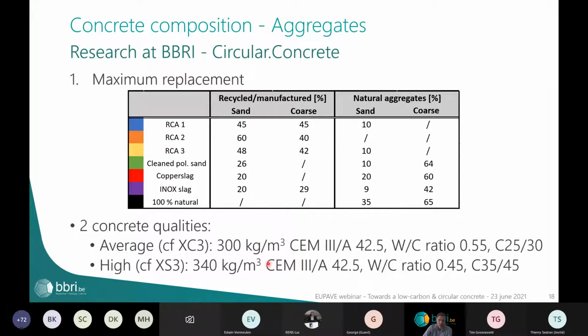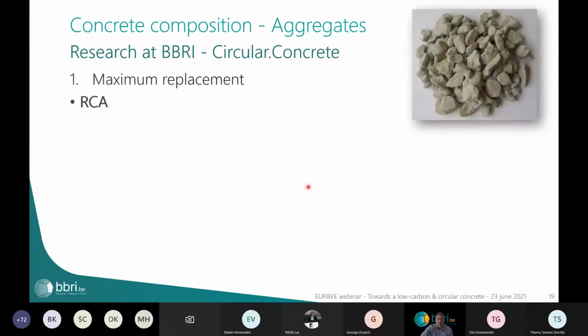We made one of average quality, which is conform the requirements of the EN 206 for XC3, which means in fact a minimal cement content of 300 kilograms per cubic meter and the water to cement ratio of 0.55. We used CEM 3A 42.5 to make the concrete, and then we looked at a high quality concrete with 340 kilograms and the water to cement ratio of 0.45. And we made concrete with that.